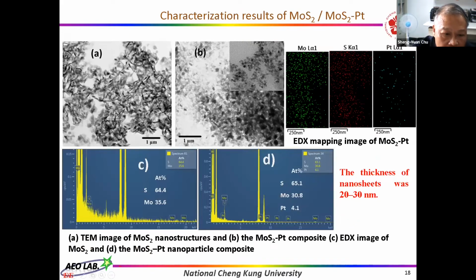These two figures show the TEM images of the MoS2 nanostructures and also the MoS2-Pt composite. And also these two figures show the EDS images of MoS2 and the MoS2-Pt nanoparticle composite. We can see the Pt is about 4.1% in these nanocomposites.